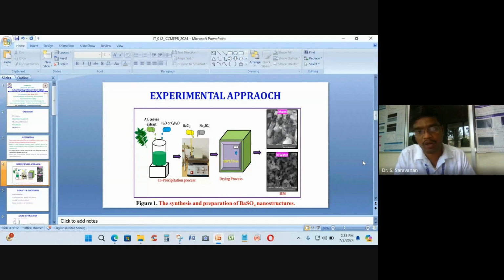So finally, I got the same morphology. You can see that in the last image, that is ethanol and DI water. It means that the solvents I have used are first water and ethanol. So both solvents I used to compare their morphology and growth. So first you can see the diagram. This is ethanol-based morphological structures. This is DI water-based morphological structures.